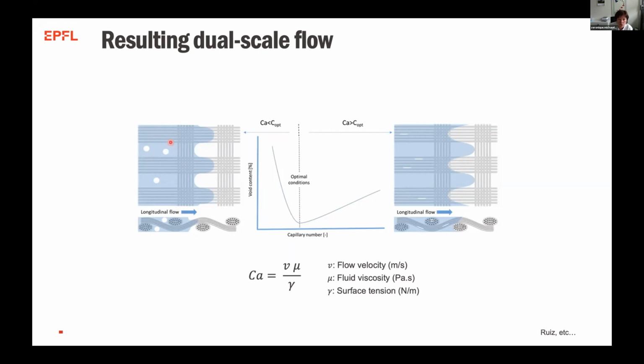And what we observe is that if the capillary number is low, we don't push very much and the velocity is very low, then capillary effects are really dominating. So the flow goes inside the fibers, the tows, and is lagging behind in between. If the capillary number, so the velocity, is very high, you will have the contrary. I push a lot, it goes in between, and the tows are lagging behind.